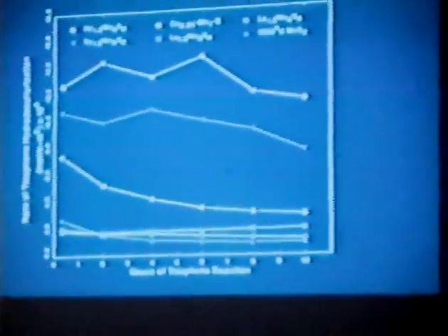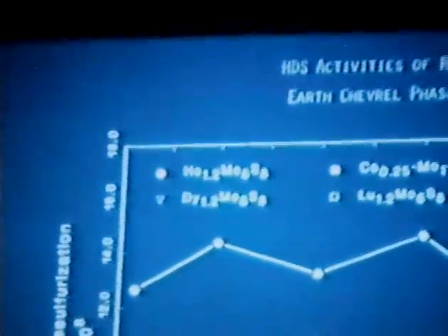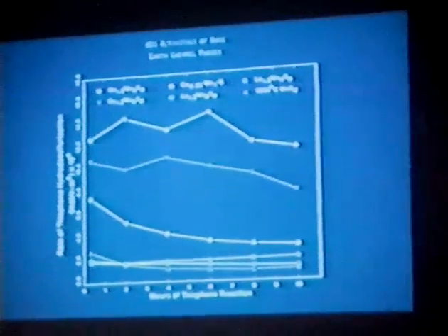If you try to just get a rough look at these rare earth compounds here, lanthanum, lutetium, dysprosium, all of these again are rather active compared to the Chevrel phase, compared to the conventional catalyst. Lutetium was a little bit disappointing here. We don't really understand why some of these are not as active as others. But again, most of them are of comparable activity on a per unit surface area basis.